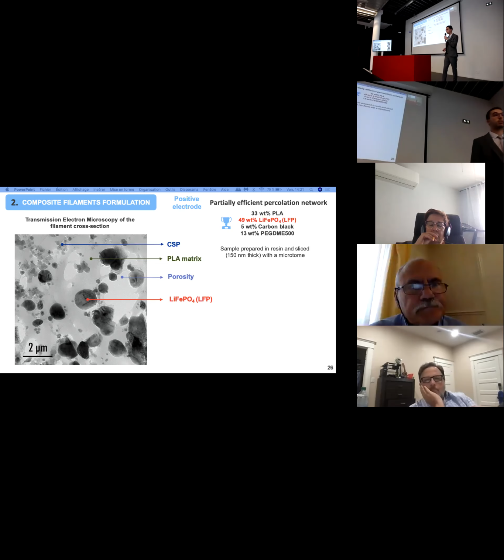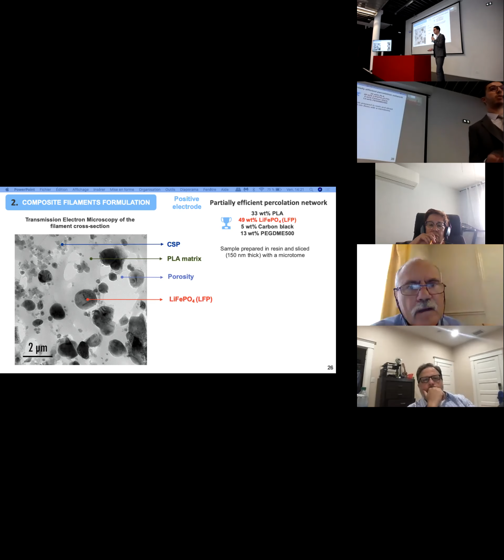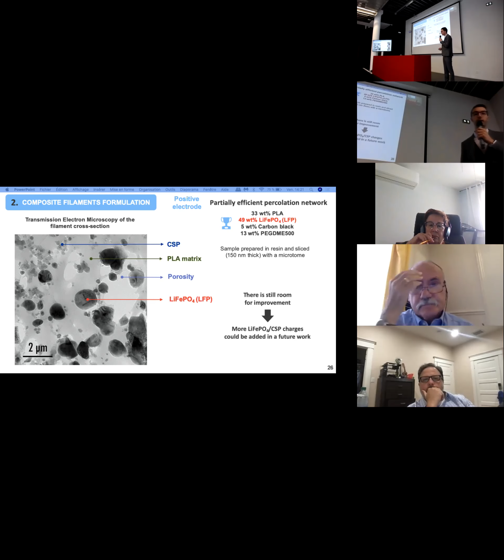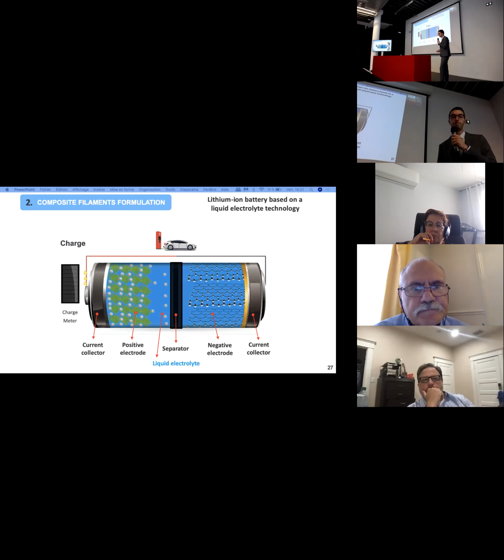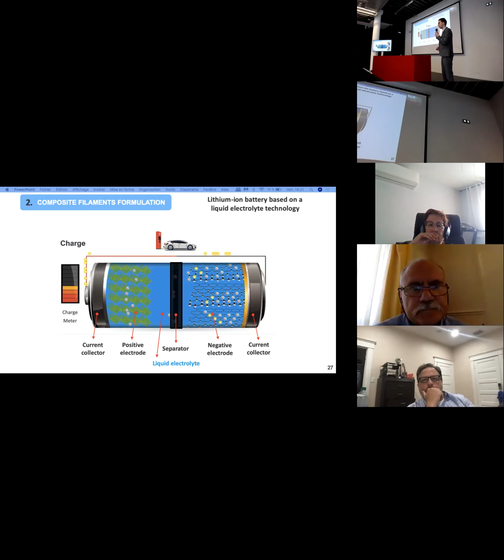Then it was needed to take a look by transmission electron microscopy to see a little bit the percolation network. And here, unfortunately, we can clearly see that LFP particles, lithium iron phosphate particles, are not really well connected to the percolation network. So there is clearly still room for improvement. In the future, we can imagine adding more conductive charges and also more lithium iron phosphate to this particular composition. So now I talked about the negative electrode, and I talked about the positive one as well.